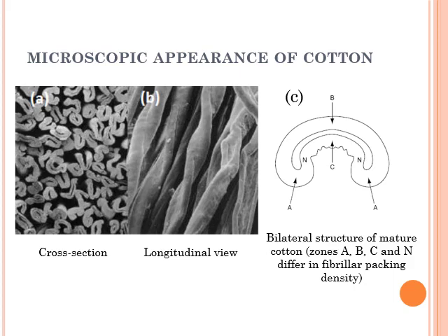Three main zones, A, B, C, as shown in the figure, have been identified by means of enzymic degradation. The rate of degradation increases from A to B and B to C, which is the order of decreasing density of packing. Between zones A and C, there appear to be limited areas, denoted by N, even more accessible than zone C.